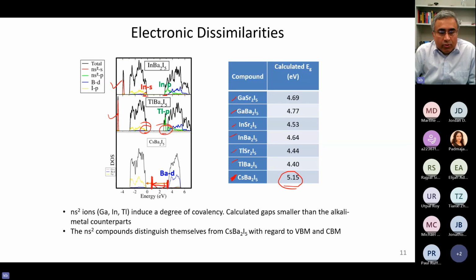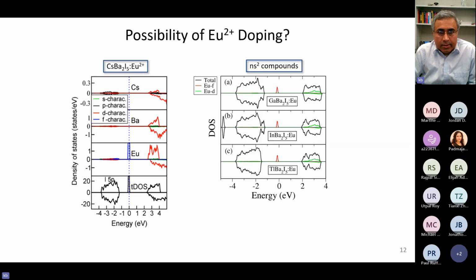First of all, let's see if we can dope them with europium. Europium is a very common activator among scintillators. Looks like if we do, europium will create half-filled F states in the middle of the gap, which is fine, which is what we want. There are more requirements, it's just one requirement. There are other details that need to be looked into. But anyway, the broadly half-filled europium F states created inside the band gap is fine. That is what we need for europium to act like an activator in these Ns2 compounds, just like we have here in cesium barium iodide.